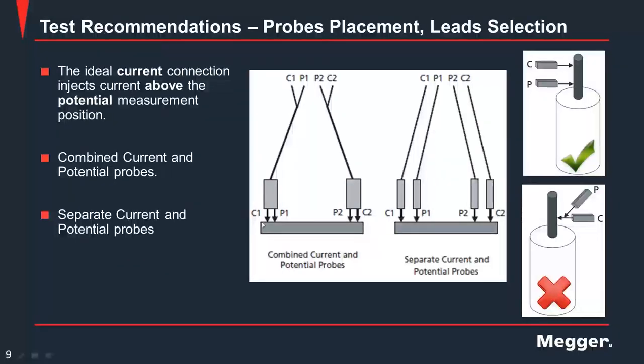But actually there is a separate terminal. C1 and P1 are separate. If you see, this is only one cable, but input and output has two terminations. So on this method, usually you can see one of the indications, either P or C, mostly P indication on the terminal. So if you know where the P for potential probe is, you can define it, and you need to put the position of this terminal so that the C or current probe is above the potential probe.